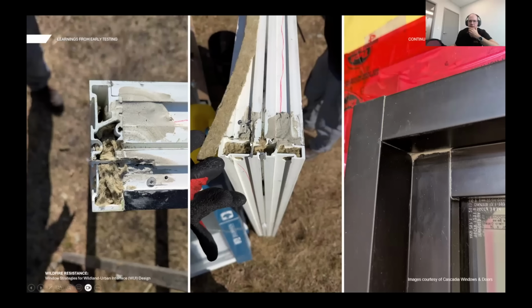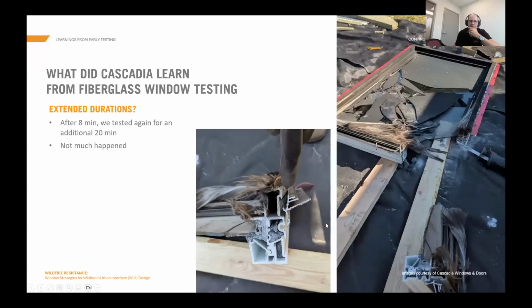But most specifically, look at the fact that there's multiple chambers. There's not just one big open cavity. Even the glazing leg that's in front of the glass has 2 walls of material and an open cavity in between. Okay, so what happens when you burn that down? Well, we burnt it, and as you can see in the sample here, it looks like all these hairs are sticking out of the surface of the burnt frame, but that's because we took hand tools and roughed it up so that we could see the glass. These are actually strands of glass that were in the profile. Before we roughed it up, it doesn't naturally do that.